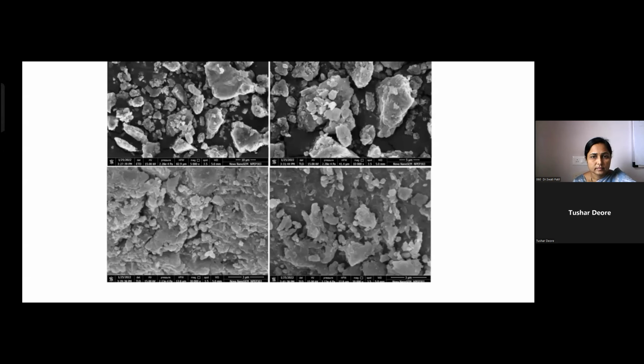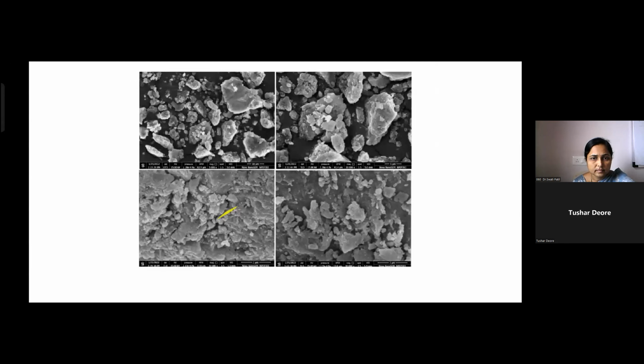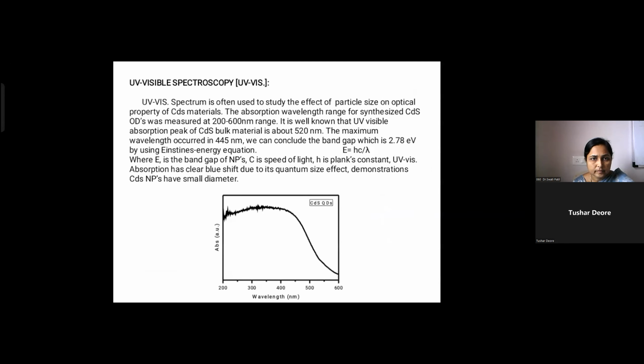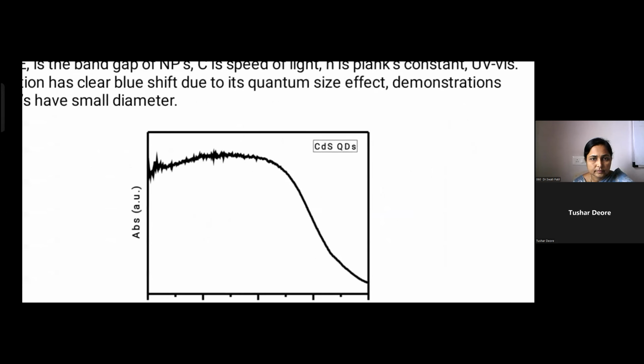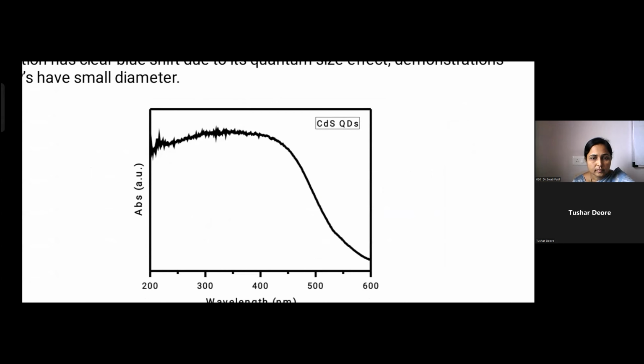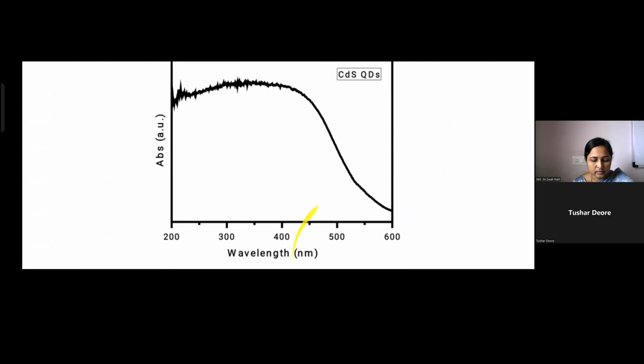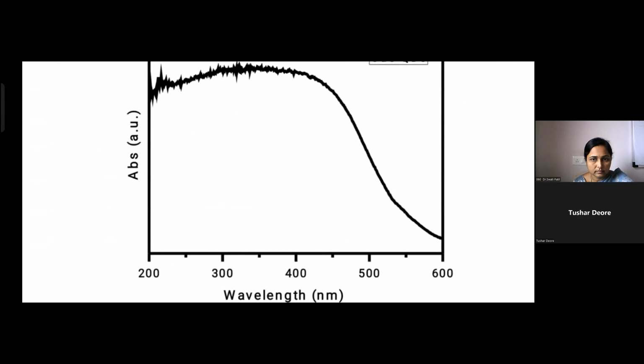My fourth characterization is, ma'am, UV-visible spectroscopy. The UV-visible spectrum is often used to study the effect of particle size and optical property. The absorption wavelength range for synthesized quantum dots was 200 to 600 nanometers, and it is well known that the UV-visible absorption peak of CdS bulk material is about 520 nanometers.